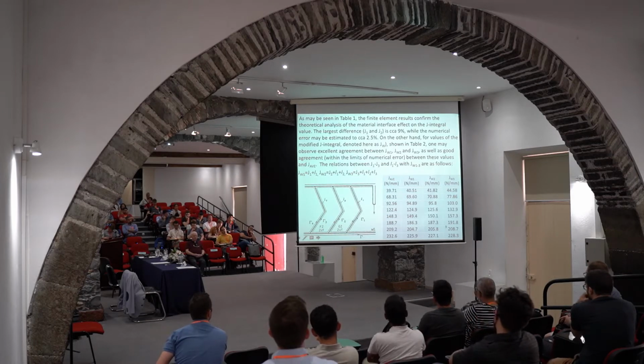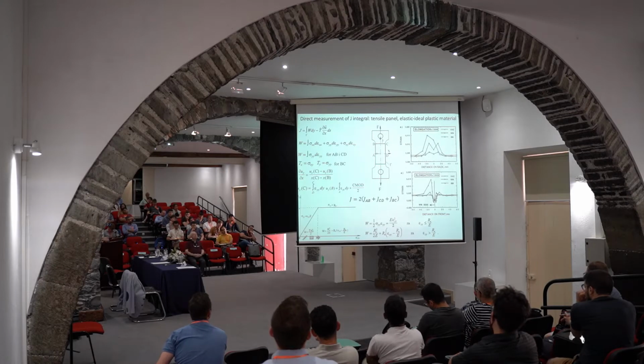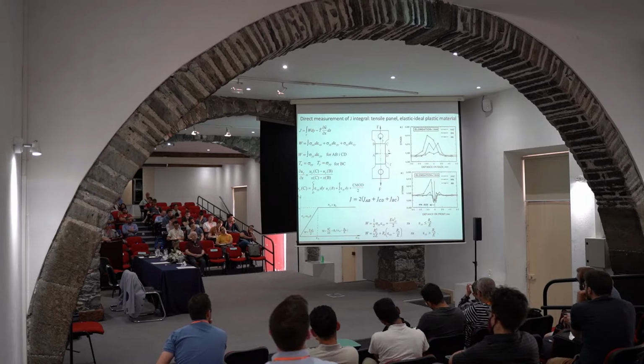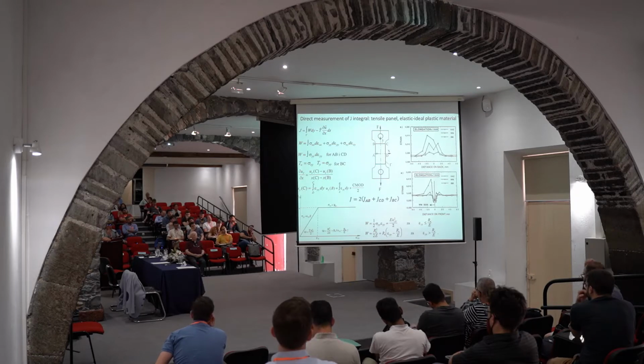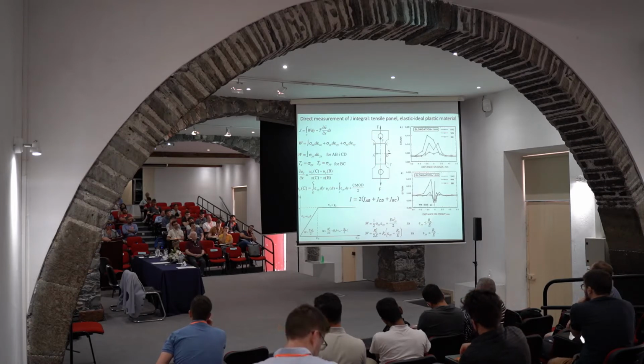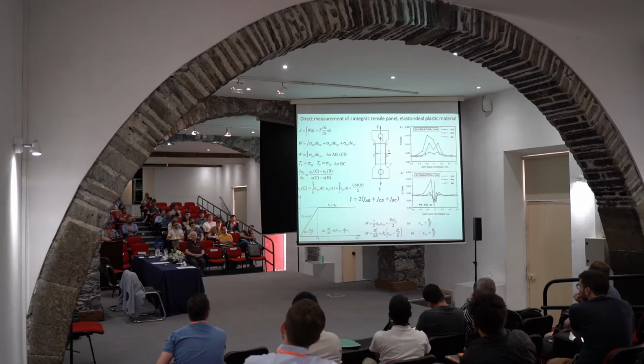So by doing that, we also prove that this direct measurement technique, which is shown here, is a valid experimental technique to measure J integral. And this is a very interesting way to experimentally evaluate J integral, and to be honest, I'm surprised that it has not been used more often.